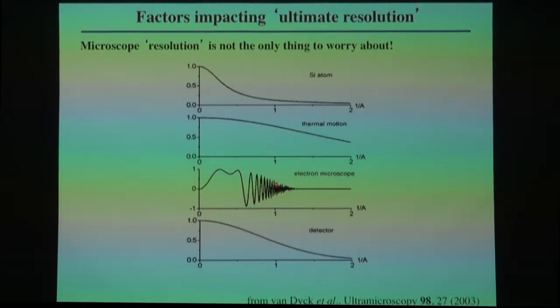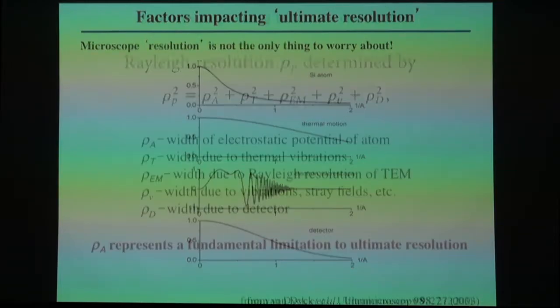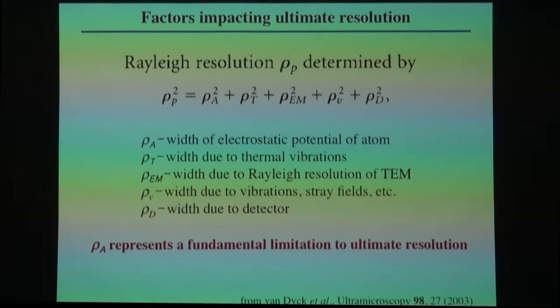Here you have the transfer function of the microscope, albeit in this case it's still with oscillations in the transfer function. You also have to worry about whether your detector is going to be adequate. So you have to go to very high magnification, and you can put all of these factors together, as Van Dyck did very nicely, and say, okay, the Rayleigh resolution is going to be affected by the electrostatic potential of the atom, the thermal vibrations, the Rayleigh criterion width due to sort of incoherent problems, and then a width due to the detector. And so this ρ_A, as he's calling it, the electrostatic potential of the atom, eventually will represent the ultimate limit to the resolution that we can get from the electron microscope.